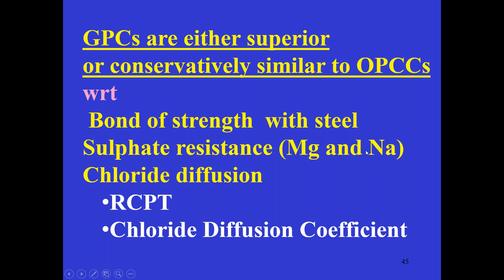And don't study sodium sulfate at all, not important. Magnesium sulfate is important, because sodium sulfate generally is not so much damaging as magnesium sulfate. So combination we can study. So anybody working on durability, keep magnesium sulfate as the main parameter, and always keep the study more than 1 year. People cannot study sulfate resistance unless they are having the previous people's specimens. Only PhD and general R&D work people can study sulfate resistance.